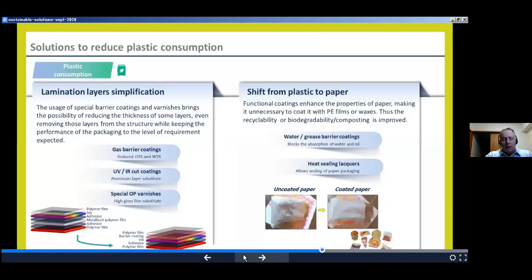But another way to reduce the dependence on fossil resources is to reduce the amount of plastic that we use in the packaging. In that sense, we are developing and proposing gas barrier coatings in order to reduce the number of layers in the flexible packaging. Instead of, for example, the metallized polymer film, we can use a barrier coating to reduce the oxygen or the water vapor transmission through the packaging. Another solution is to offer UV blocking coatings or infrared blocking coatings that protect the packaging with less plastic in the final packaging. And also high gloss varnishes for the surface, also in order to reduce the external layer that gives the high gloss to the packaging.